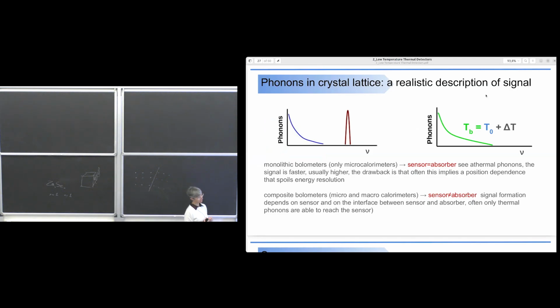The problem here is that you need a model, and you can find completely different values in the literature. To my understanding, you should ask a solid state physicist, but it has a lot of connection also to the kind of mechanisms that are active in your absorbers. Because one way to transform a high energy phonon into a thermal phonon is scattering, which can take place on the external surfaces by reflection, or on any kind of defect that you have in the crystal. So it then depends on the size of the crystals, of course.